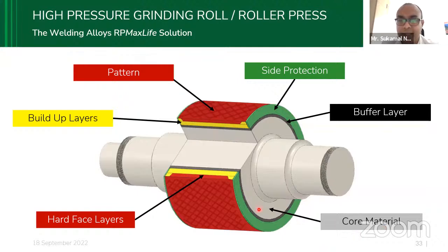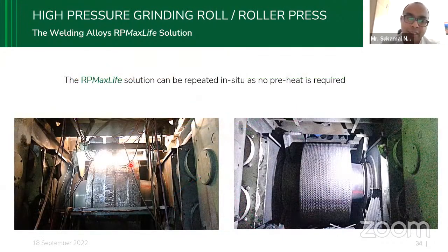The core material is there. Then first we have a build-up layer. Then you have a hard face layer. Then you put a pattern, and a side protection is always there to help protect the side wall of the rollers. This is what it looks like in the industry. You can see that this is worn out, and we are doing the rebuilding. After we do the rebuilding, this component looks like this.